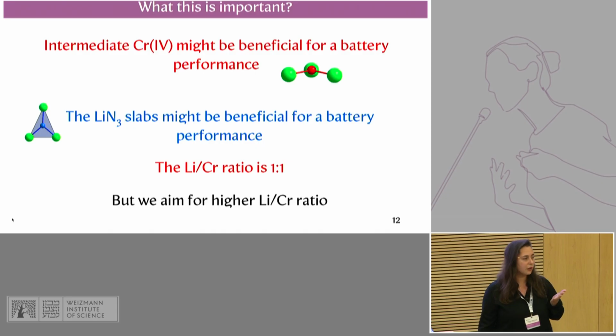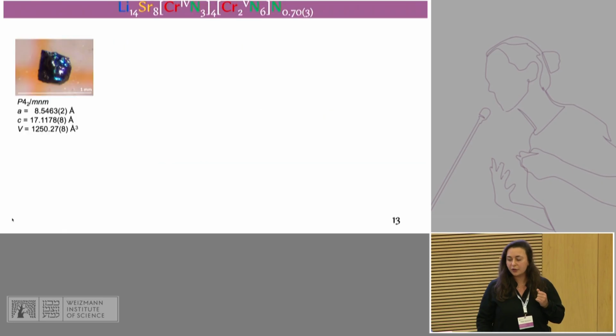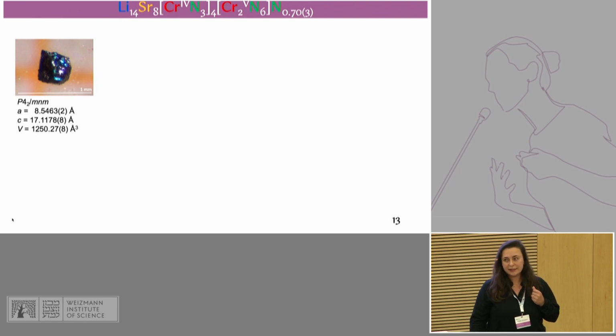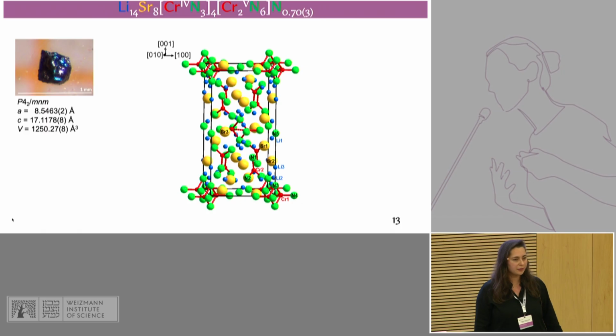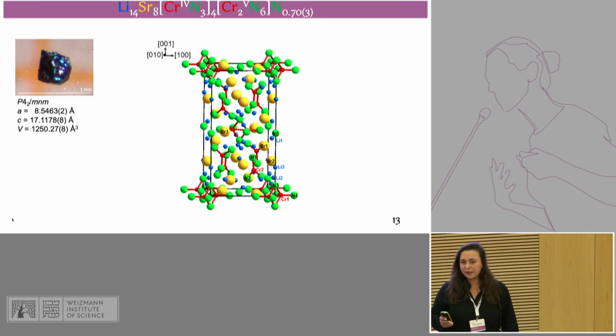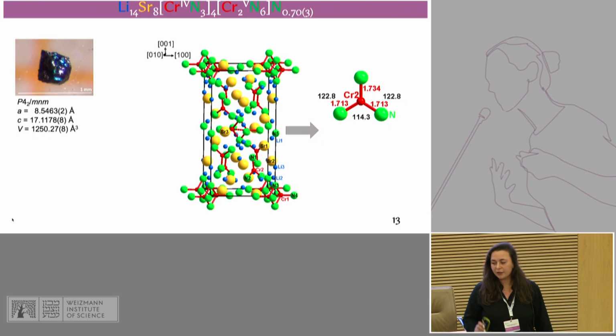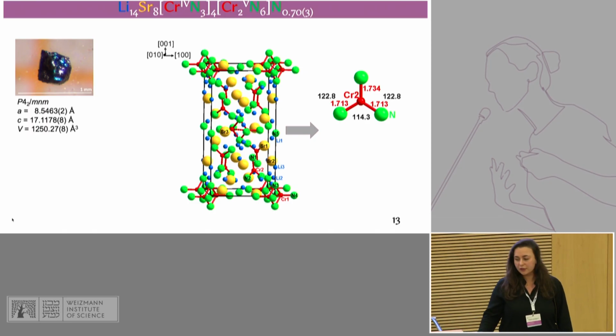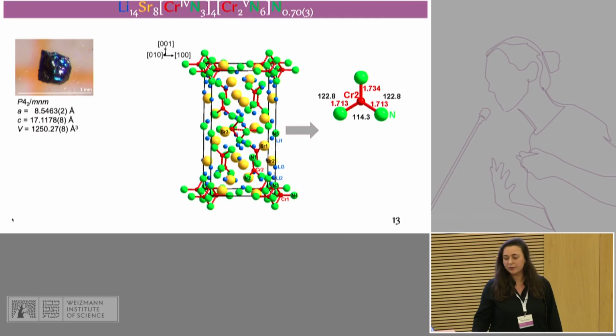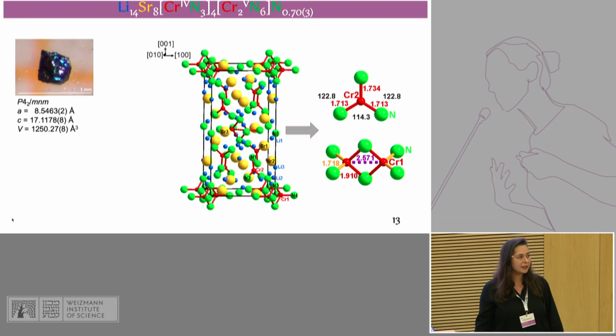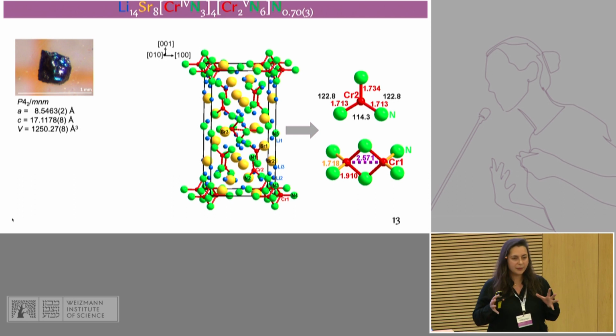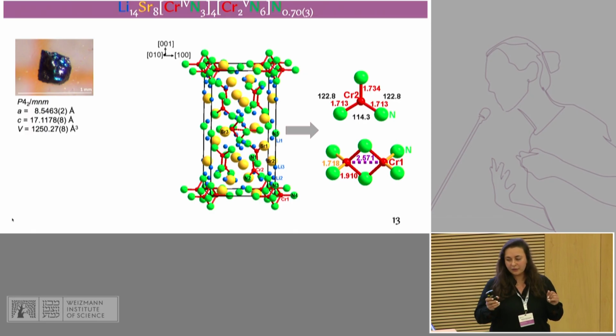Therefore, we performed another synthesis and were able to synthesize also black metallic crystals. When we obtain the crystal structure, it can be visualized in the following way. You immediately see that it's much more complex than the previous compound, right? We can also divide it into simpler parts. Firstly, chromium units. We saw it in the previous case, a slightly pyramidal trigonal unit. But this compound also has double tetrahedra, Cr2N6 units. This combination of two different units in one compound is the first case in this family of compounds, and actually in nitridometalates, which was observed here.